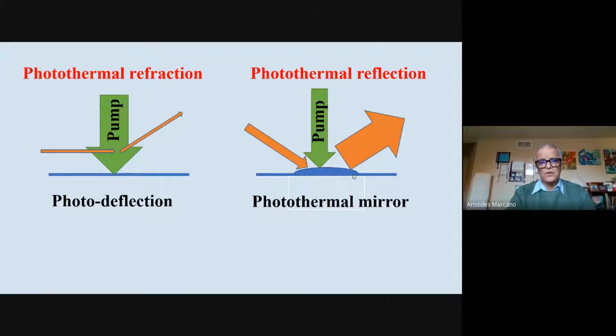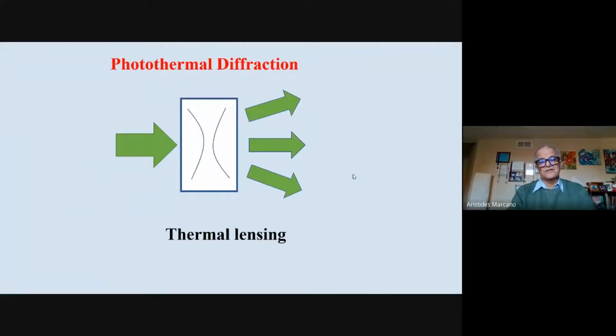The other thing we do is the photothermal diffraction. We say diffraction when something is hitting or blocking the light somehow, but this is not actually blocking. It's just that we have some changes in the refraction index inside because of the heating. That's represented by this concave parabola right here. It mostly represents that the refraction index decreases with the temperature, and close to the center where you have more intensity, you have less refraction index.